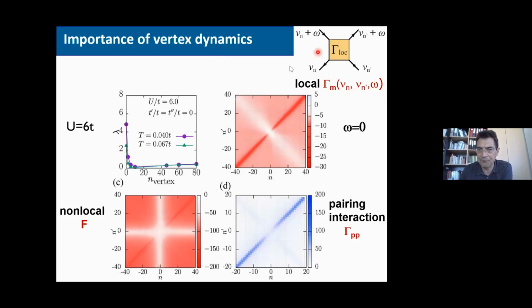That is shown here. So you have here the two frequencies. The third bosonic frequency is set to 0. From this local vertex, you then calculate in a Bethe-Salpeter ladder the full vertex for the antiferromagnetic spin fluctuations, and from that you get the superconducting pairing vertex.